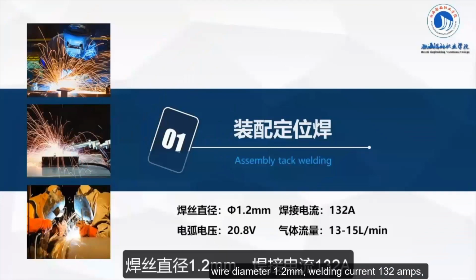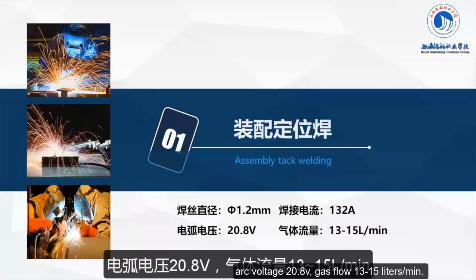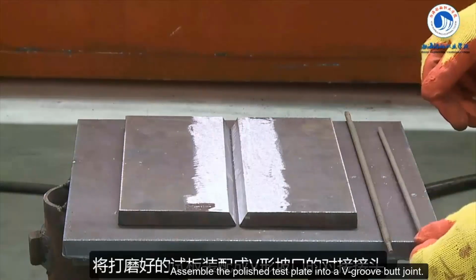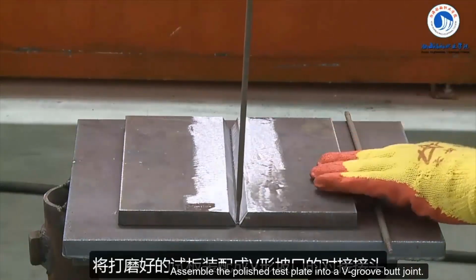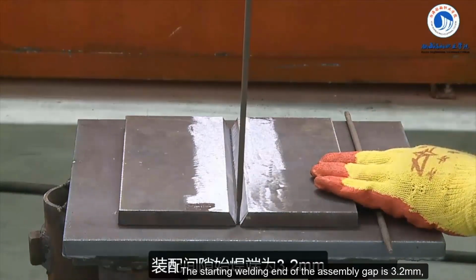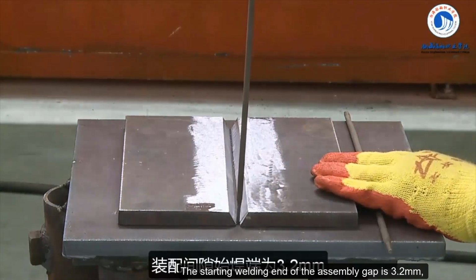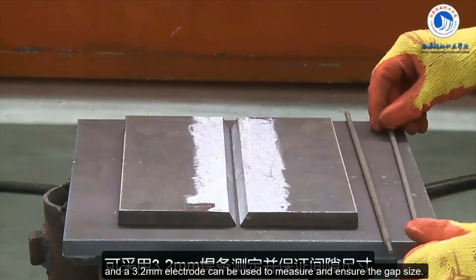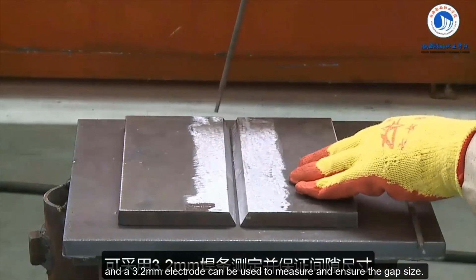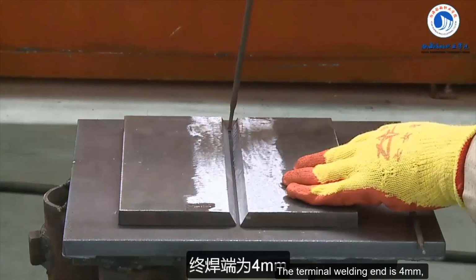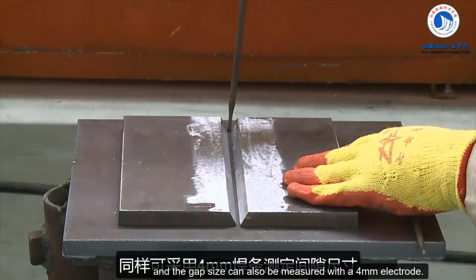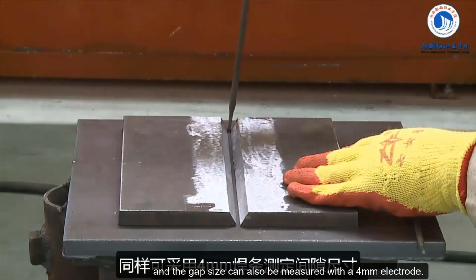Assembly tack welding. Wire diameter 1.2 mm, welding current 132 amps. Arc voltage 20.8 V, gas flow 13 to 15 liters per minute. Assemble the polished test plate into a V-groove butt joint. The starting welding end of the assembly gap is 3.2 mm, and a 3.2 mm electrode can be used to measure and ensure the gap size. The terminal welding end is 4 mm, and the gap size can also be measured with a 4 mm electrode.